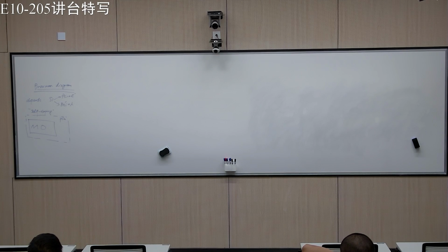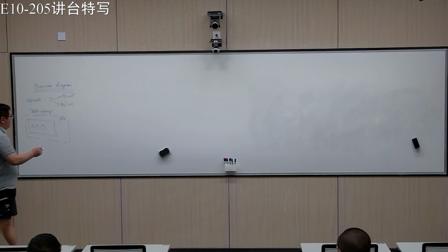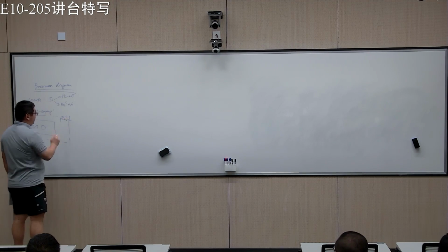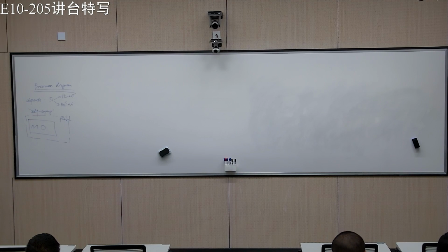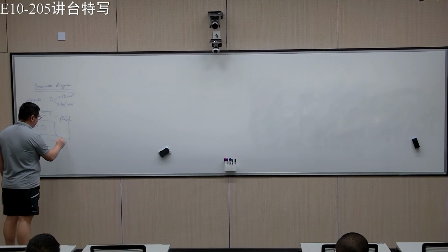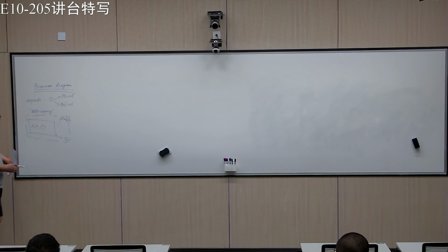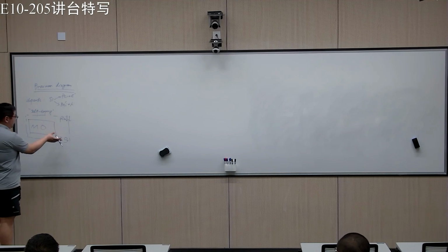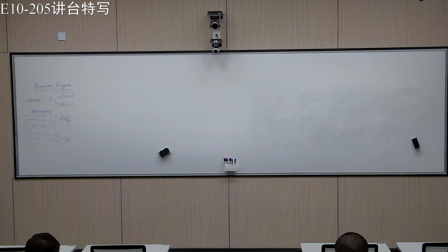Okay. So now let's say I lower the partial pressure in the surrounding environment, and we heat it up. If the temperature is sufficiently high, it will reach a new equilibrium. We're going to remove some oxygen from the sample so that we can be in equilibrium with the PO2.